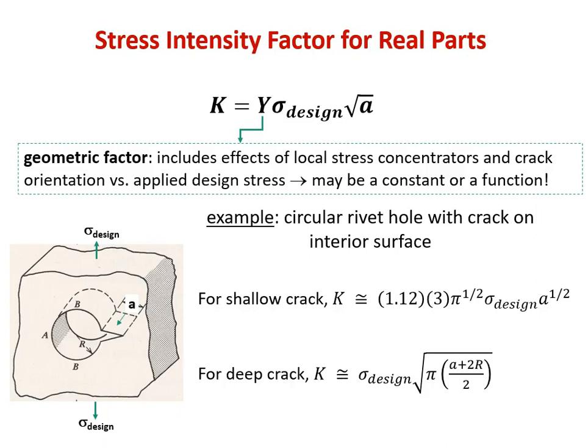We can generalize this to other loading scenarios, other crack shapes and geometries other than just a semi-infinite plate and an elliptical crack. And when we do that, we define K a little bit differently, but it has the same essential components. So if we define a stress intensity factor generally that can be used for real parts, we define it as K, means the same thing, stress intensity factor, equals Y times sigma design, which is the applied stress to the whole part, times the square root of a, which is the crack length again.